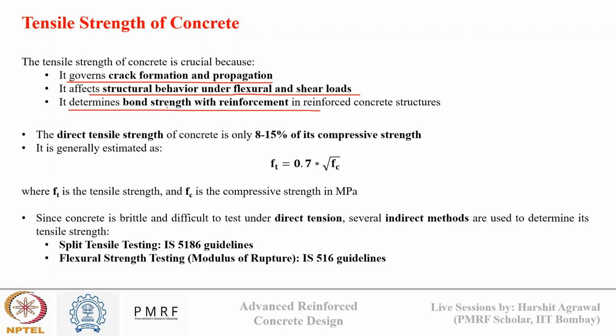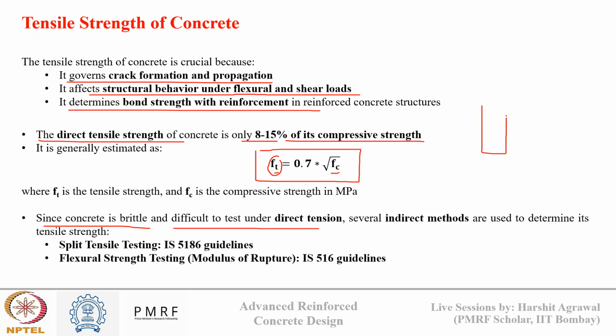Okay. So the direct tensile strength of concrete, usually it is only 8 to 15% of compressive strength, and it is generally represented by this equation. So Ft is 0.7 times under root of Fc. So this is tensile strength and this is compressive strength. However, since concrete is brittle, it is very difficult to do direct tensile testing. So suppose this is my cylinder, I can't just directly do this tensile test on concrete, because it is brittle in nature. So that's why we use several indirect methods to determine tensile strength of concrete, and the methods that we use are split tensile testing and flexure tensile testing.